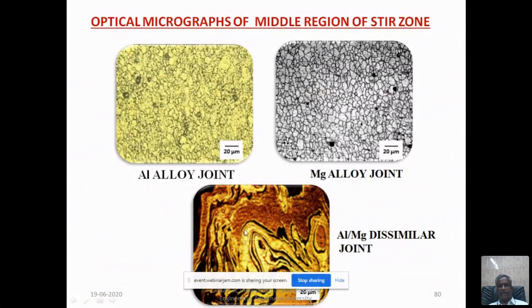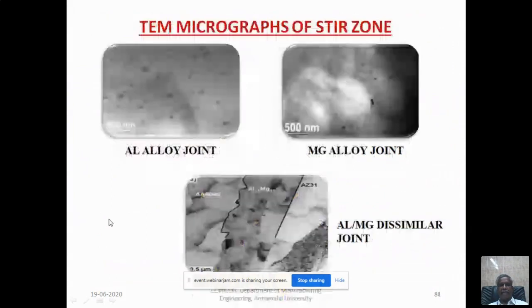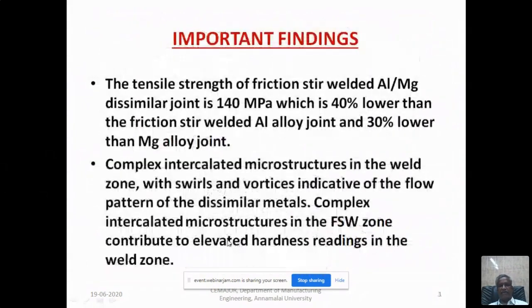The dark region is magnesium and the white region is aluminum alloy. One layer is aluminum and the next layer is magnesium, and they form like that. There is no proper bonding, but a mechanical bonding took place because of this stirring action. This is the TEM, electron micrograph. The precipitates are fine and uniformly distributed in the similar joints, but in the dissimilar welding there are a lot of intermetallics. You can see Al12Mg17 and others occur here. That reduces the strength. But we successfully welded, and it is 40% lower than the aluminum alloy and 30% lower than the magnesium alloy, but we are able to achieve 140 megapascal tensile strength in the dissimilar joint.